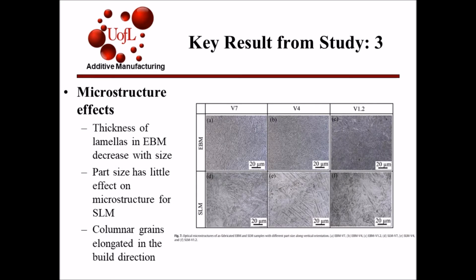The graphic shown shows the optical microstructures of EBM and SLM samples with different part sizes along vertical orientation. As shown in the graphic, the EBM samples were composed mostly of alpha lamellas, whereas the SLM samples contain much thinner and longer martensitic lathes. Thickness of the lamellas in the EBM samples decreased with size, which explains the increase in strength properties with the decreasing part size. The thickness of the lathes in the SLM samples did not vary with size.